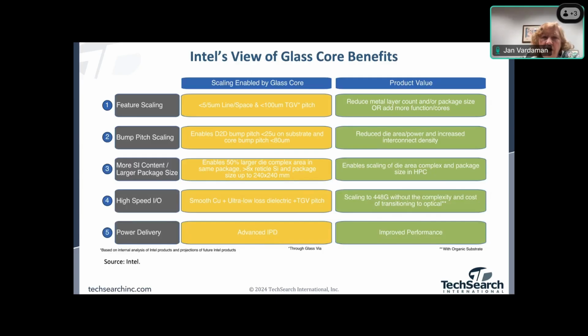So they've really been pushing hard on the idea of the advantages of a glass core by using it to scale their features. Say you could go to less than 5 micron line and space, maybe less than 100 micron TGV pitch, and bump pitch scaling. They think you could go to less than 25 micron bump pitch on the substrate. And you remember what they mostly are known for is their EMIB technology, where they have an embedded silicon bridge in a laminate substrate. So the minimum pitch they've done so far on that is about a 45 micron pitch in production. So this would enable them to get to a finer pitch to support the finer pitch of the bump devices. And so there's also, they think they can do more silicon content, larger package sizes.